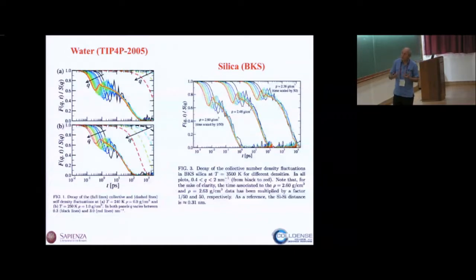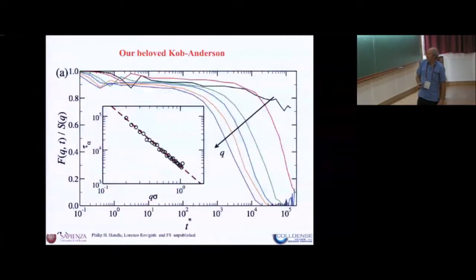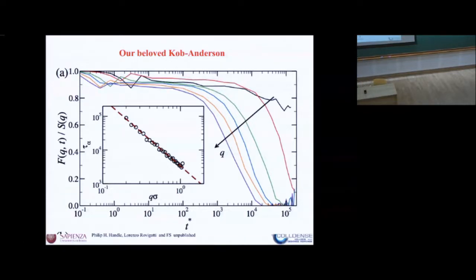And of course, at a certain point, you will cross over to hydrodynamics, but if the system is glassy, this crossover will be at extremely small Q. Close to the glass transition, this crossover will be of the order of meters. So you cannot see the real hydrodynamics. Okay, but let's check also our beloved Kob-Andersen model, and that's completely different. Here, the alpha relaxation time scales with Q squared, the density. That's a very clear Q squared dependence. And if you think why this is happening, this comes from the fact that, wake up.